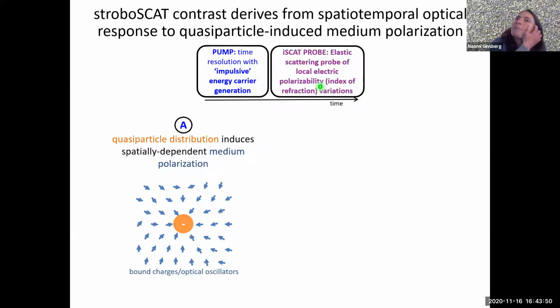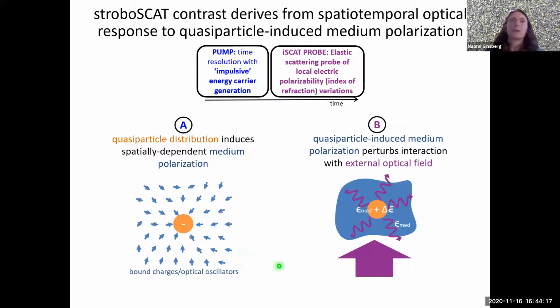So first of all, the field from the quasi-particle distribution should induce some spatially dependent medium polarization. So you can think of these as all your little bound oscillators oscillating at optical frequencies, as we typically do. And then we need to think about what happens when the probe shows up. So you have this spatially dependent quasi-particle induced medium polarization. And this perturbs the interaction with this external optical field. So what I'm really asking is, how much easier is it for the optical field to do the polarizing of these little dipoles here, rather than whatever the quasi-particles are doing to constrain them? Is it easier or is it more difficult?